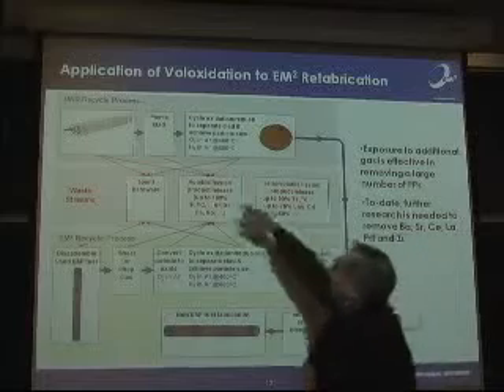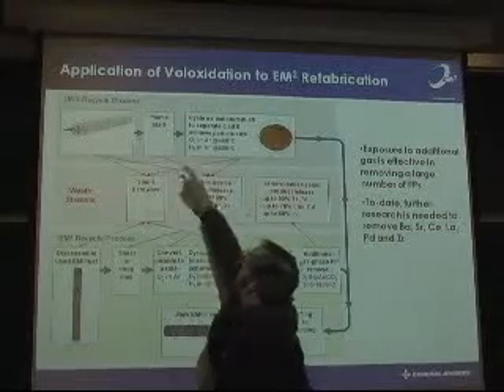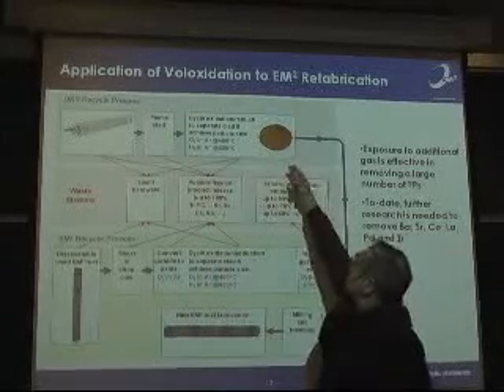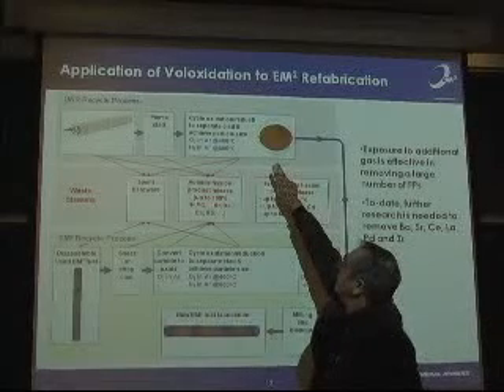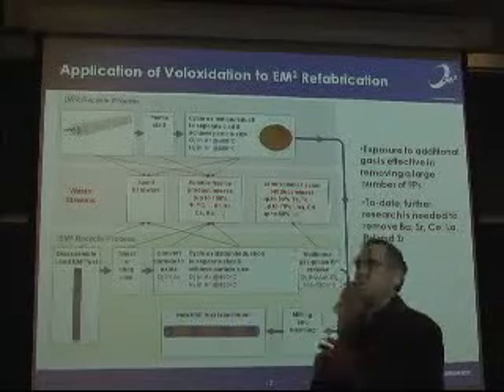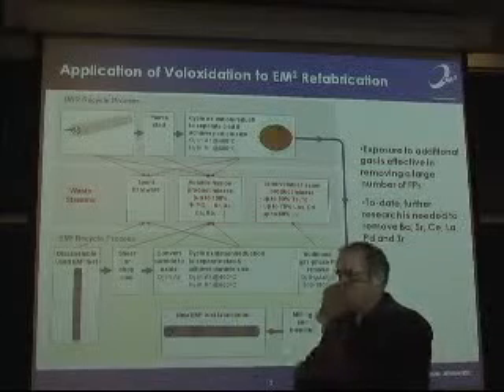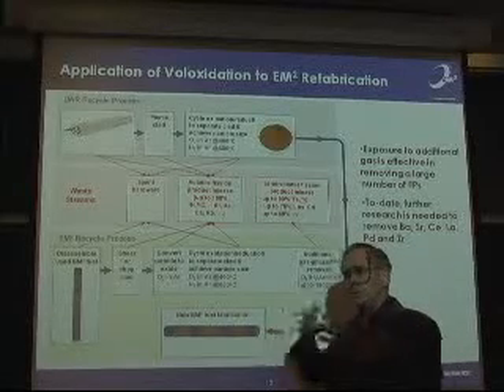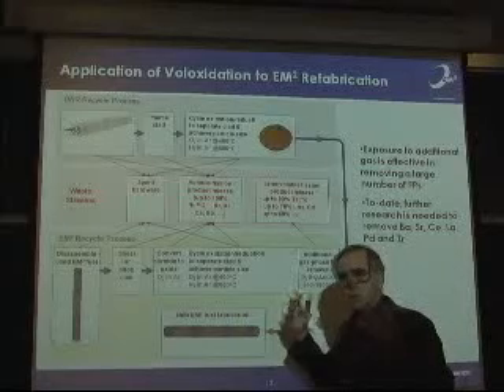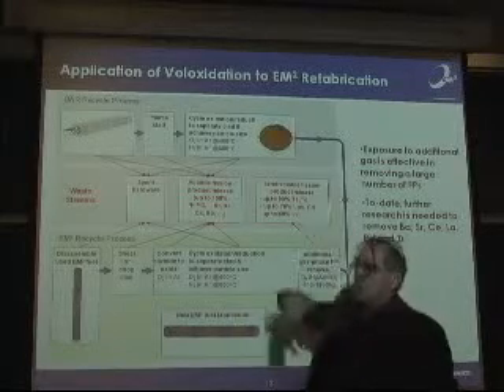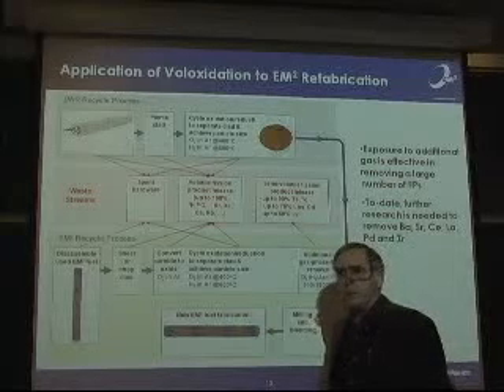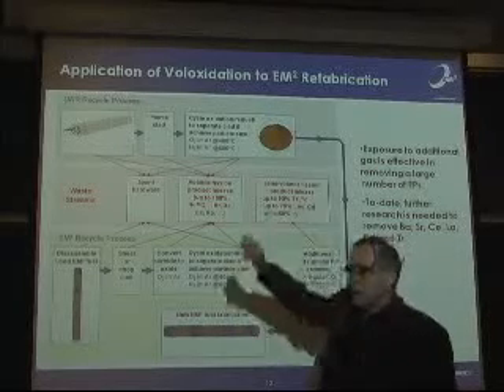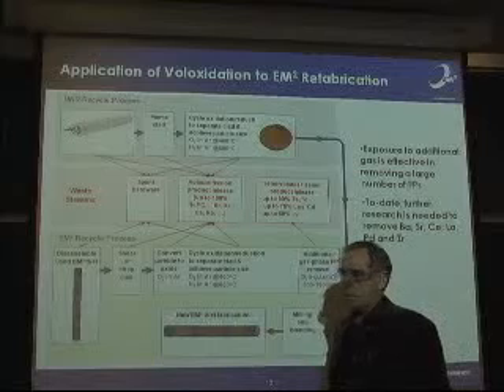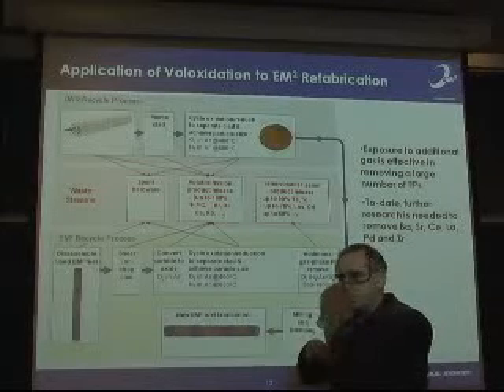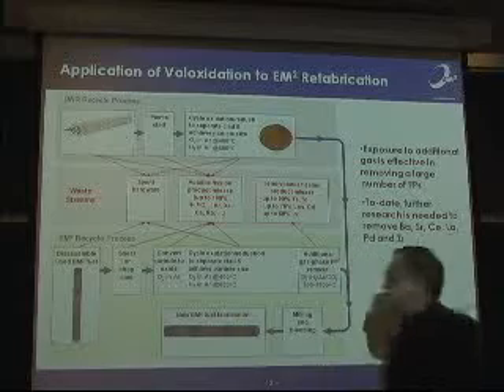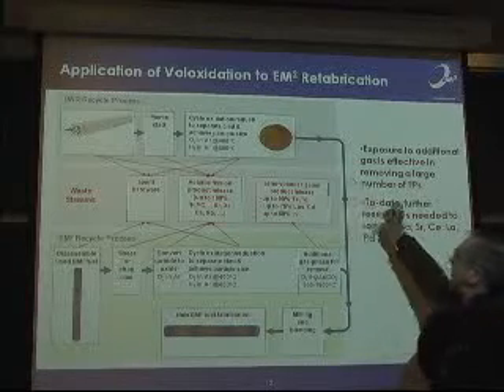So what do you do? You take an LWR fuel rod, you pierce the clad, and then you subject it to alternate oxidizing and reducing environments, which converts UO2 to U3O8 to UO2. So you go through volume expansions and contractions. This pulverizes the material to a very fine powder after 3 cycles of this, and you just literally pour it out of the fuel rod. That was always a problem, how you can get the pellets to not stick to the zircaloy cladding. But they found this works quite nicely.